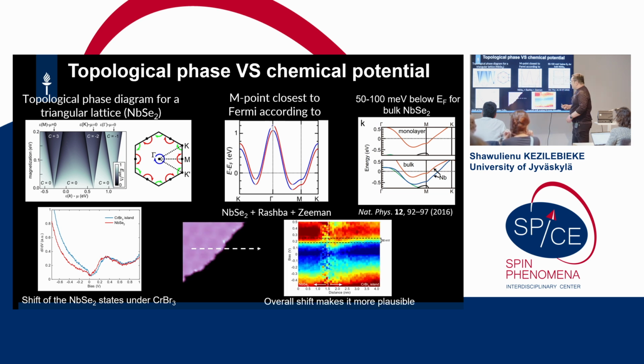So you can also measure this shift precisely by looking at this kind of line cut spectroscopy and just following the d band. And from this, we can get roughly 80 millivolt shift. So this puts us roughly in this category. But I will tell you more about it later; in the end, this is not that important. For now, you just need to know we are in this region.